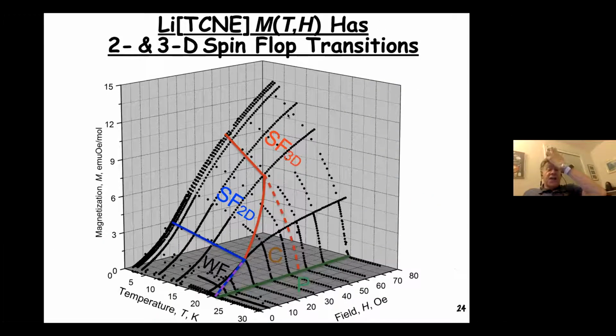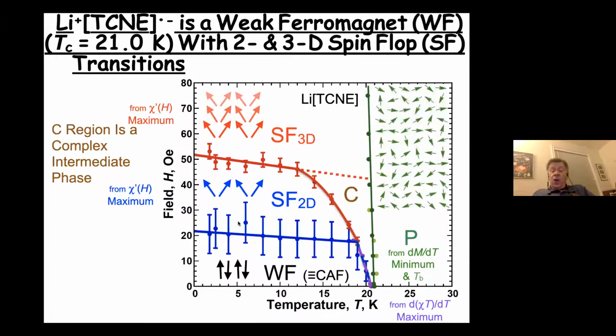And if we look at all this data in 3D, we can see that in fact, we have magnetization on the z-axis, temperature on the y-axis, and the x-axis is field. And we can see the manifold of data and the phase transitions. And using this data, we can amplify a 2D phase diagram where basically at higher temperature, we're in the paramagnetic phase. And as I mentioned, we have a phase boundary to the ordered magnetic phase over here.